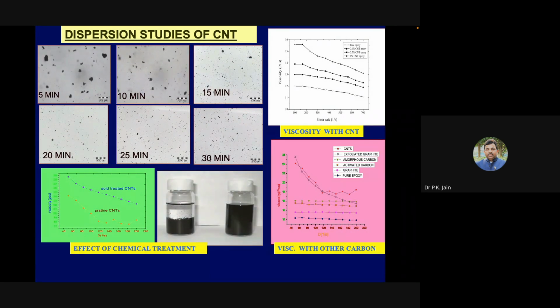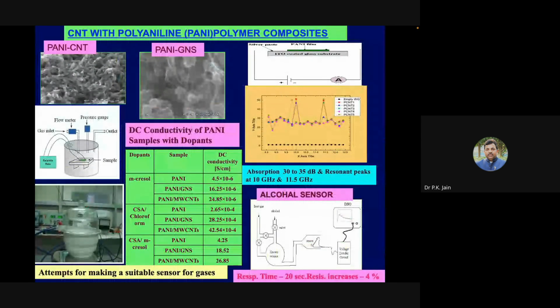Because you require a proper surfactant, a very small quantity of surfactant, proper functionalization of the nanoparticles, depending on where you want to disperse it, and then disperse it. Because the challenge in dispersion is the charge on the particle, and this charge is measured through zeta potential. How to control that charge is a skill. When you cannot control it, you have to disperse it in such a way and put a surfactant layer in between so that the particles will not agglomerate, and once they do not agglomerate, they will not settle that easily. We have also developed some sensors, EMI shielding, and put it into different types of materials.